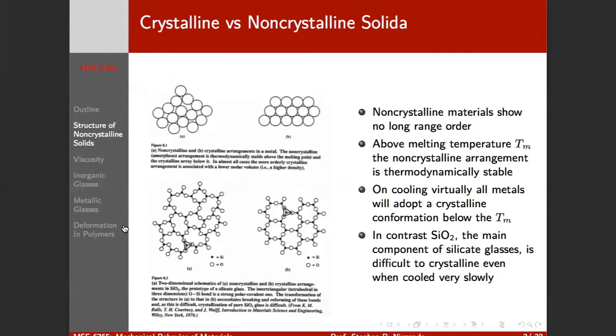By the bonding, you have to have this tetrahedron. This is the expected chemical bonding of your local neighborhood. So in this glass structure here, all of the atoms are individually happy, because they have the same local configuration. It's the long range and medium range order that breaks down.